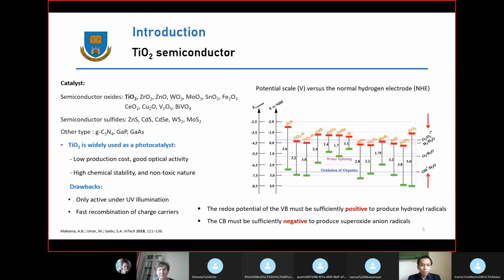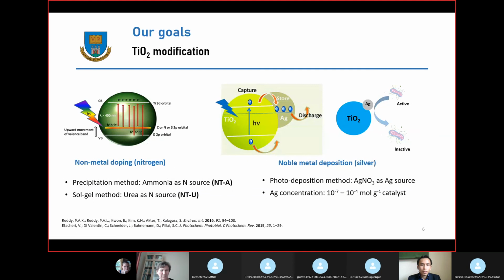Therefore, to tackle this problem, our goal is to modify the titanium dioxide with different elements such as metal or non-metal elements. Firstly, we modified the titanium dioxide with nitrogen to reduce its bandgap energy and thereby extend its light absorption into the visible region. To overcome the fast recombination process, the silver nanoparticles were attached on the surface of the catalyst to capture the photogenerated electrons and then extend the lifetime of the charge carriers. Besides that, the presence of the silver nanoparticles on the surface of the catalyst is also expected to inactivate microorganisms such as bacteria.